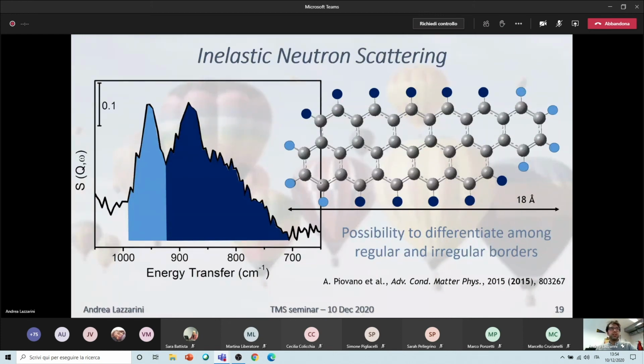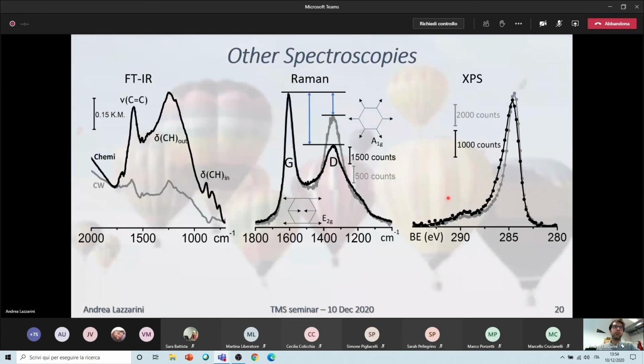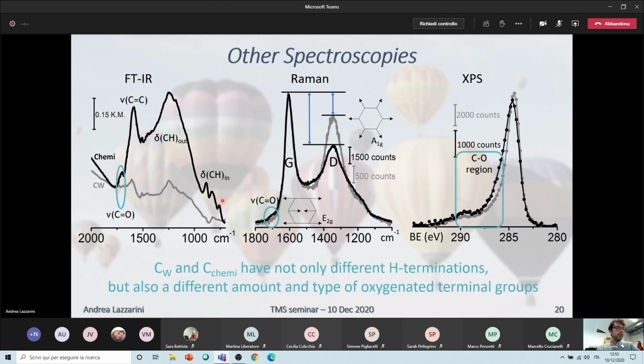But this was concerning just the effect that the different hydrogen terminations can have. One other possibility was to study, with other spectroscopies, infrared, Raman, and X-ray photoelectron spectroscopy, the effect of functional groups. And in fact, all the spectroscopies were highlighting a difference between the two samples in oxygen content. This was coming from different functional groups like esters, acid groups, aldehydes, lactones. And this had a tremendous effect on the nature of the catalyst itself. So these two have not only different hydrogen terminations, but also a different amount and type of oxygenated terminal groups.